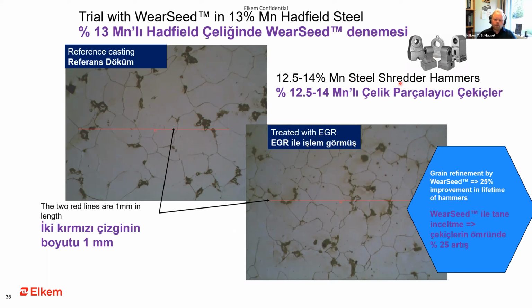So this was shredder hammers that were made in a manganese steel, around 13% manganese. This is the reference casting. You see here, this red line here is 1 millimeter in length. So it's quite coarse grained. And then when they started using EGR, you see here, this red line here is still 1 millimeter, but you have much smaller grains. And what the customer of the foundry saw was they achieved a 25% improvement in lifetime of the hammers when they started to use EGR.